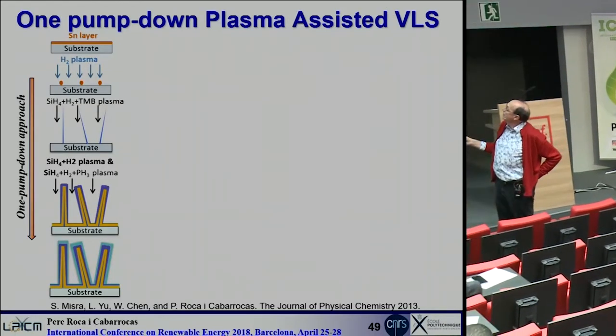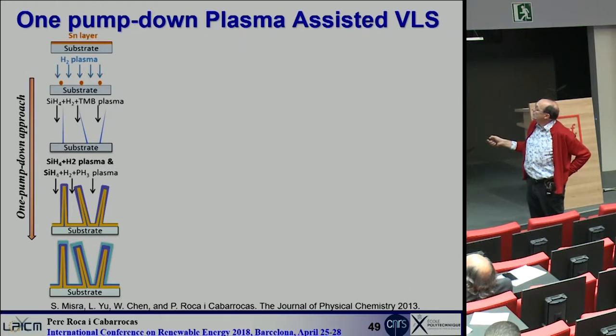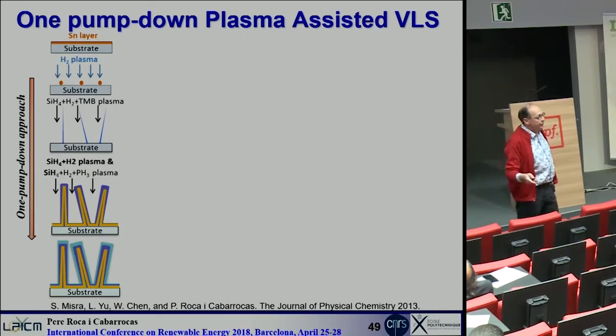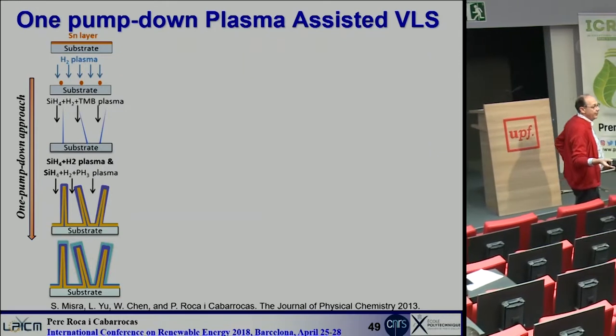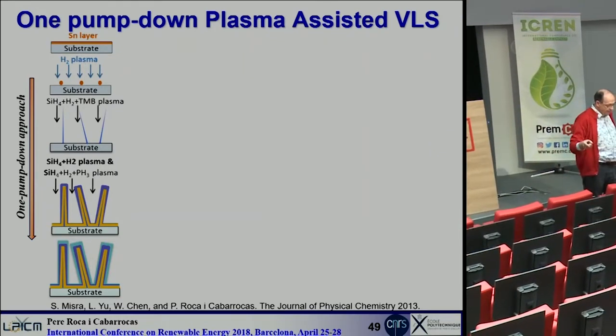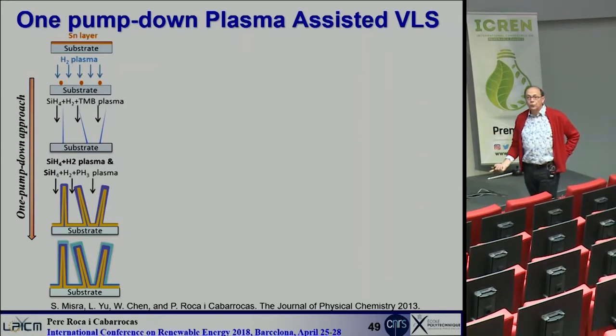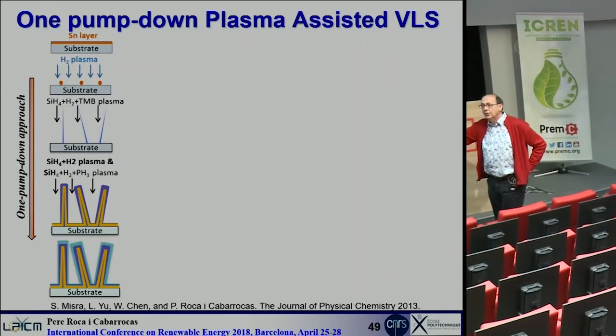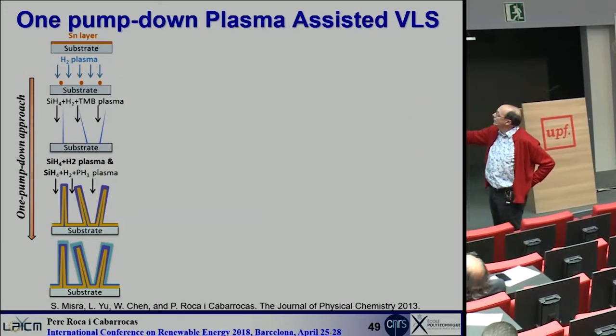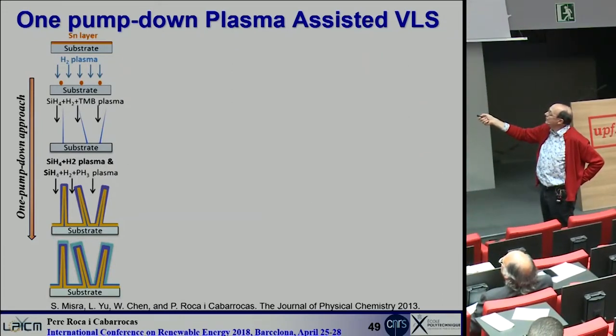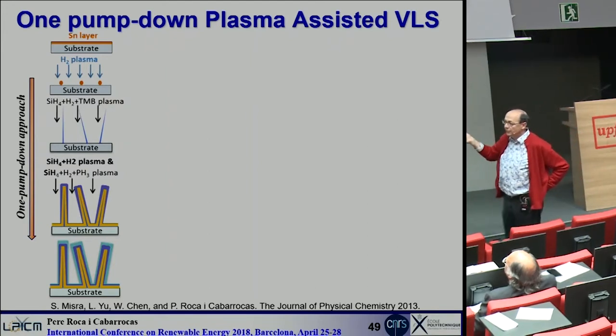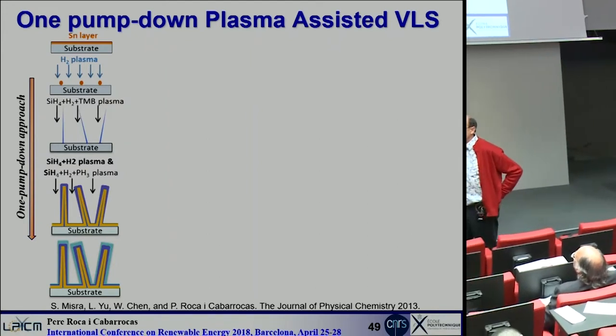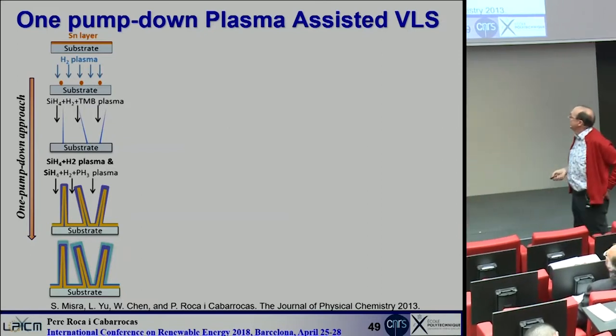And by doing that, when we have this thin layer, if we run a hydrogen plasma, we can get this thin layer into thin drops, which are liquid at 230 degrees. You switch from hydrogen to silane, and then you can promote the catalyst-assisted growth of silicon nanowires at low temperature in your PECVD reactor. You put silane and TMB, you have a p-type core. Then you change the process. You go for an intrinsic layer. You change the process, you put phosphine, so you are making your PIN radial junction in one pump down process. Simple. Okay.